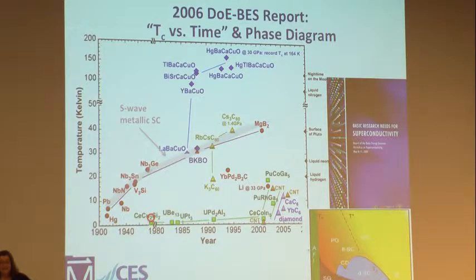I don't care if it's D-wave, if it's not electron-phonon coupled, there's some spin thing going on there, or excitonic, whatever it is. What we have found out is that those Bogoliubov-de Gennes equations work just fine there. You can put in a D-wave kernel. If you have multiband, you have to futz around a little bit with it. But pretty much, we understand what's going on down here. We might not understand what's causing the electrons to form Cooper pairs, but they do form Cooper pairs. So we do have an understanding of that state.